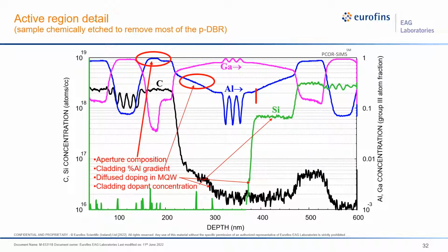this profile starts at a depth of less than 100 nanometers. And that means that we have etched off almost the entire P-DBR layer before starting this analysis, and we've developed very sophisticated etching techniques where we can stop the etch at any layer in the DBR that we choose. And this allows us to analyze the active region under higher depth resolution conditions than we could use if we had to analyze the entire structure.